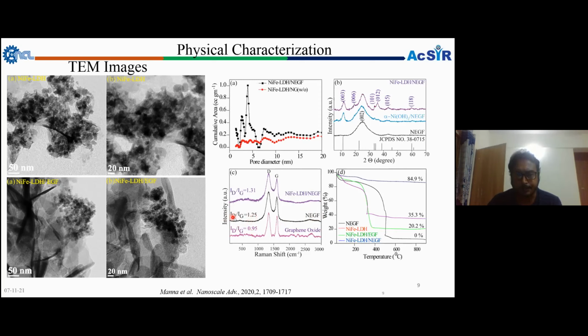That is because of the higher amount of defect creation in the nitrogen doped entangled graphene, which was already shown in the FESEM image. But after incorporating the nickel iron layer double hydroxide over the nitrogen doped entangled graphene, not much change is observed, because the nickel iron layer double hydroxide does not cause any distortion of the graphitic structure. The higher ID by IG value compared to graphene, with the defects still increasing, may be helpful for electrochemical performance. In electrochemical performance, the ID by IG value should be optimum, which helps give better activity as well as durability. Because if the graphitic nature is very low, there is a chance of more corrosion, as I already showed in the introduction slide.